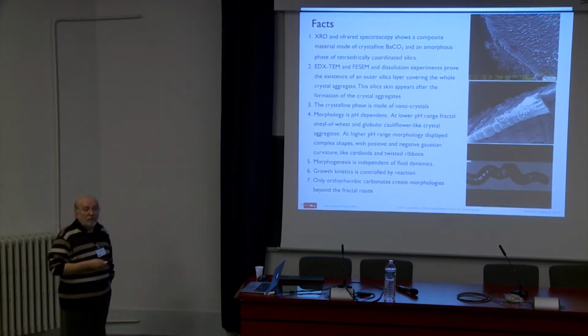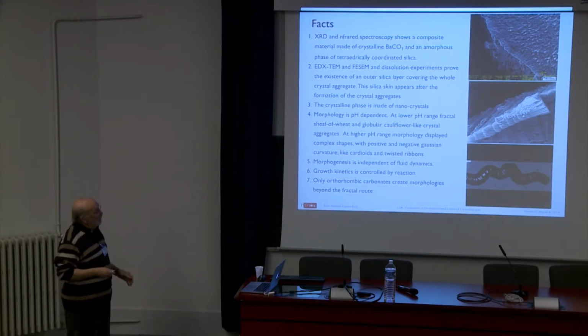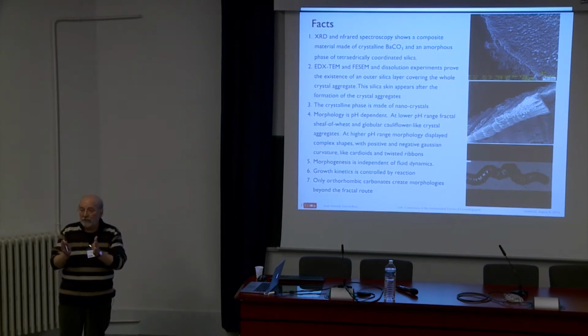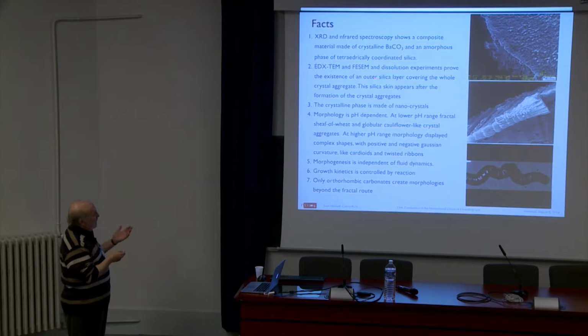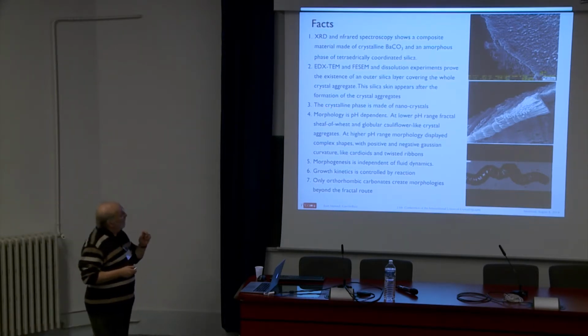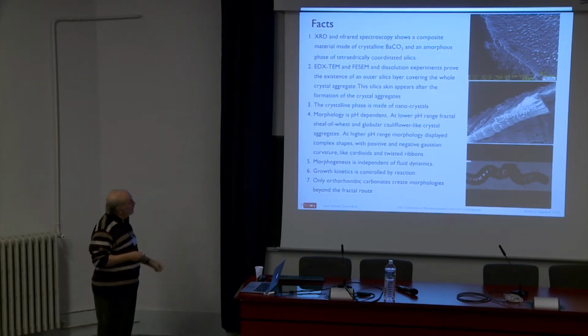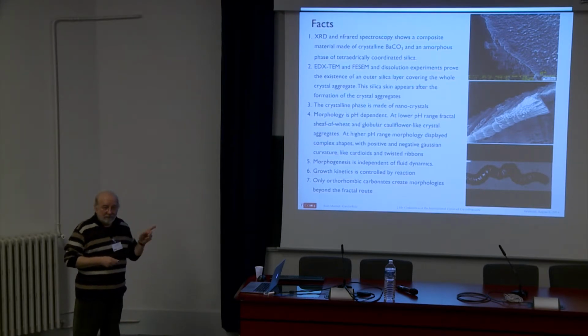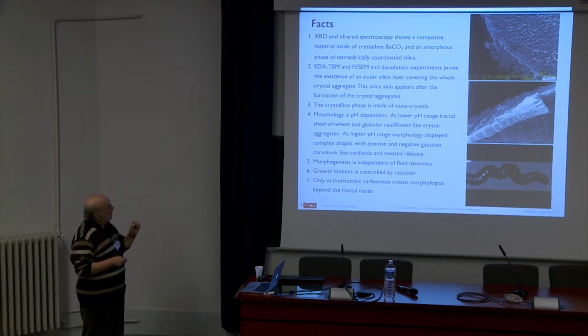They are made by millions of nanocrystals of the carbonate that are self-oriented one to each other. Okay, so that you have orientational symmetry but not translation symmetry. Okay, and there are two phases. One phase is a silica polymeric non-crystalline phase, and the other one is a nanocrystalline carbonate phase, which are, as I told you, self-oriented one to each other. These are nanocrystals with a characteristic size of 100 nanometer by 40 nanometer. In all cases, it's orthorhombic phases. So it's key here that calcite doesn't form this kind of morphology, only aragonite type structure. So strontium carbonate, barium carbonate, and calcium carbonate in aragonite structure.